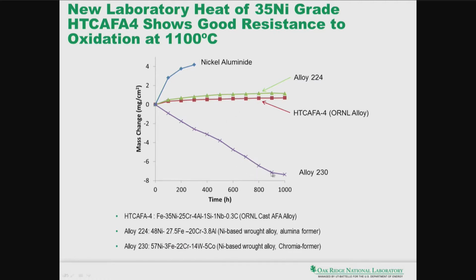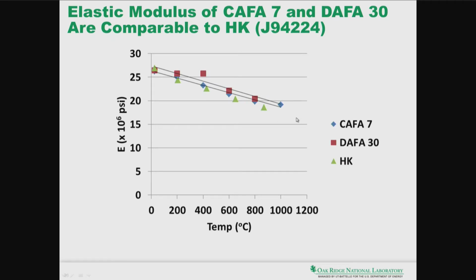And what is actually shown here is an alloy 230, which is also a high nickel alloy, but it is a chromia-former. So clearly, again, the alumina-forming alloys come up on top with the good performance of the HTCAFA-4 at temperatures up to 1100C. So clearly, we have shown you the data that illustrates the potential for oxidation resistance in these groups of alloys.